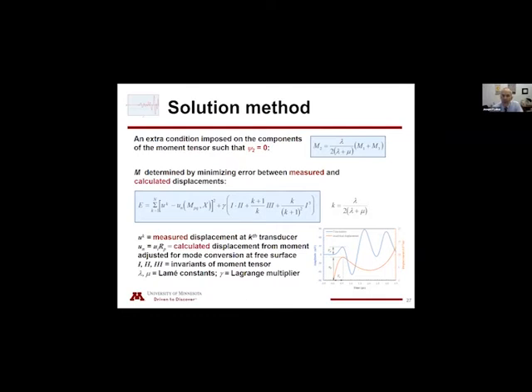The way we need to do that, because we do use the solution that's written out in terms of the moment tensor, we have to guarantee that the intermediate value of M takes this form, because we want the model that's associated with crack only. So we claim we can measure the displacement at the position of the sensors. We calculate the displacement that the moment associated with that event would produce at that position. We do adjust for the free boundary in terms of a mode conversion that takes place at the free surface. And this other part is the constraint that we must impose to get the crack-only model.